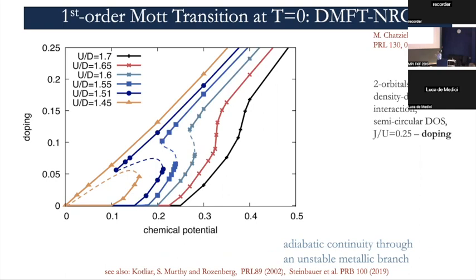Now, what's interesting is that if you increase U, you will keep having this structure of connected solutions, which then unfolds slightly, and in the end you get, at some given larger U than the U where the coexistence was happening, a continuous, monotonically growing solution. Now, what's interesting is that this adiabatic continuity is preserved in both parameters of the phase diagram. We are at zero temperature, I forgot to say.